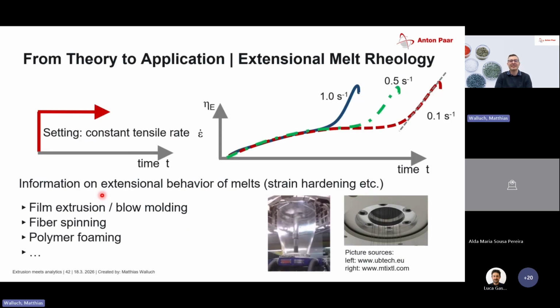What is measured is a little bit different than standard rheology, as you can see in the curves. So we see the extensional viscosity over time, and each curve is just one single sample. So we apply one extensional strain rate, for example 1 reciprocal second, 0.5 and 0.1, and we can see here that the material, depending on the speed, behaves differently. And in this case, we see that the material goes up, so the viscosity at a certain point starts to increase, and this is so-called strain hardening behavior.